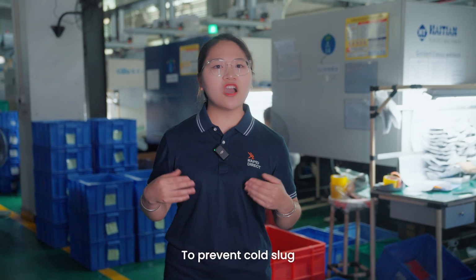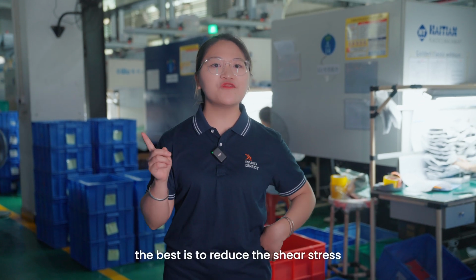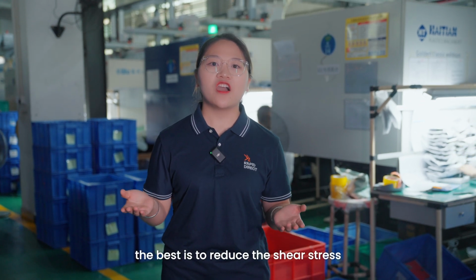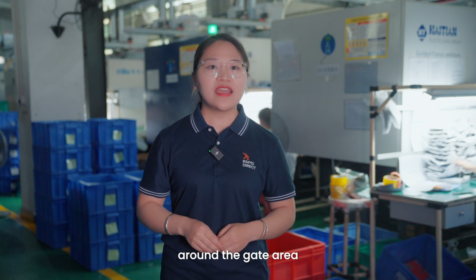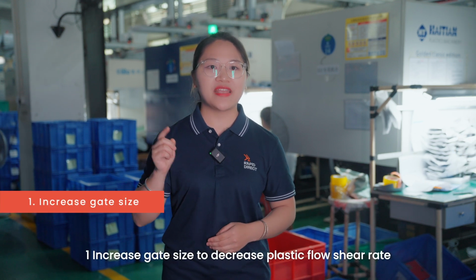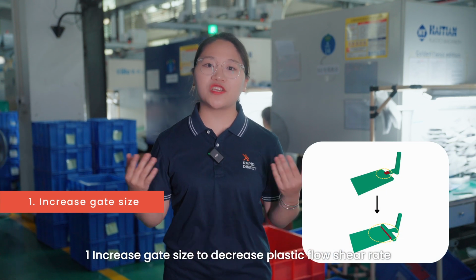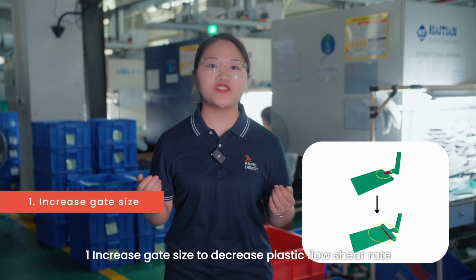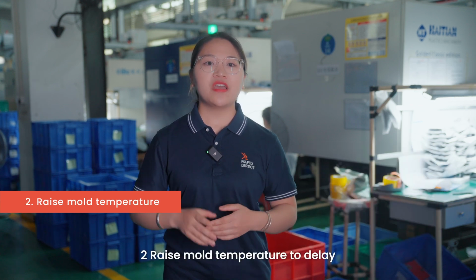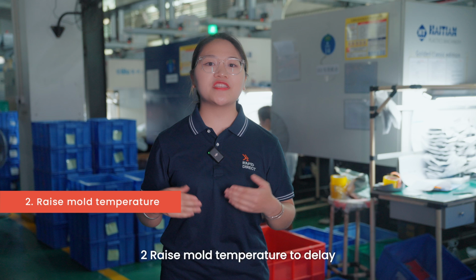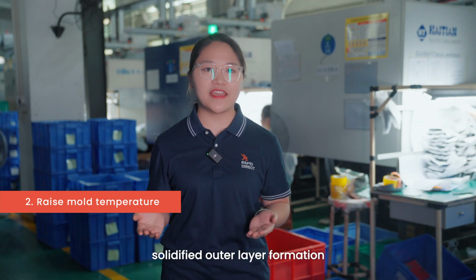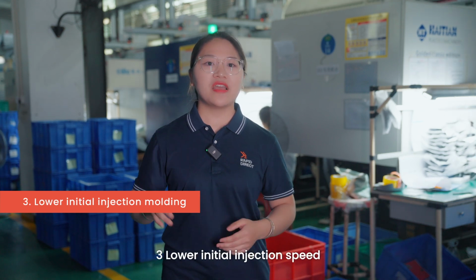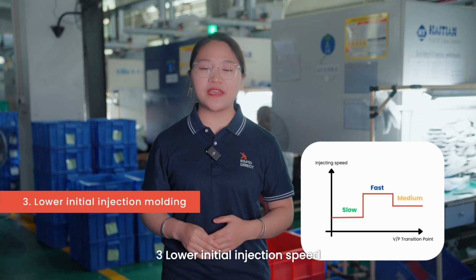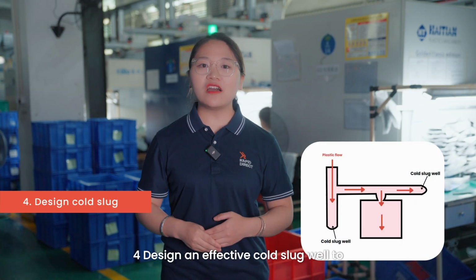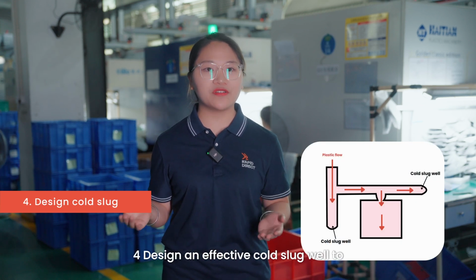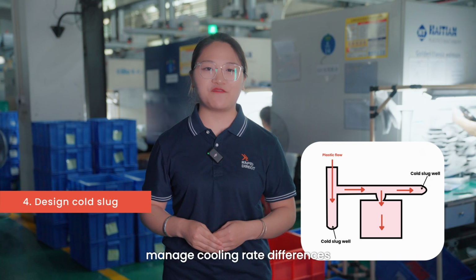To prevent cold slug, the best way is to reduce the shear stress around the gate area. Here are some strategies. 1. Increase gate size to decrease plastic flow shear rate. 2. Raise mold temperature to delay solidified outer layer formation. 3. Lower initial injection speed. 4. Design an effective cold slug well to manage cooling rate differences.